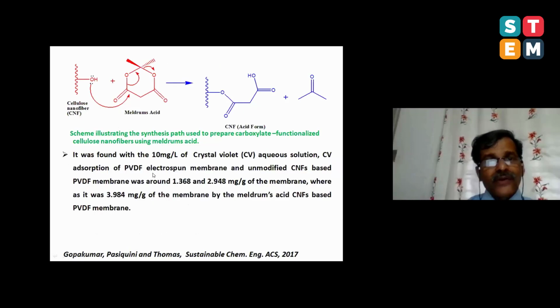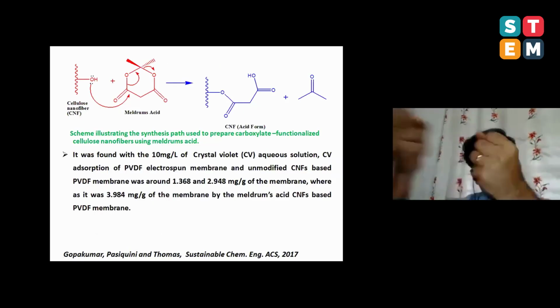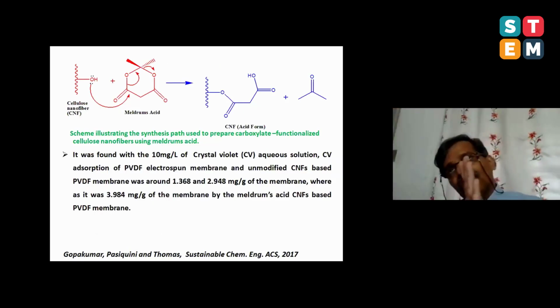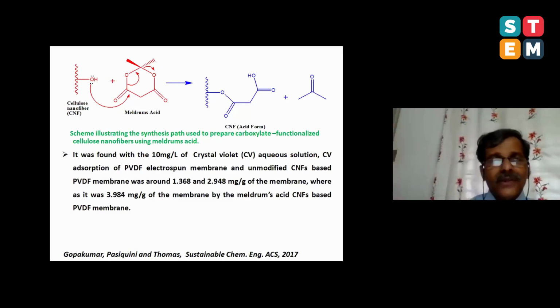I will show you what we have done. We bought a commercial filter, which is made of a PET, PVDF combination. And the top of this filter, we modified with nanocellulose. Before that, we made a small chemistry. This is nanocellulose. I've shown one of the hydroxyl groups. We modified this with Meldrum's acid. We used a clean chemistry route, and we could introduce COO minus group on the nanocellulose surface.